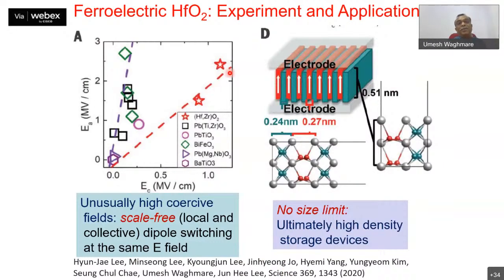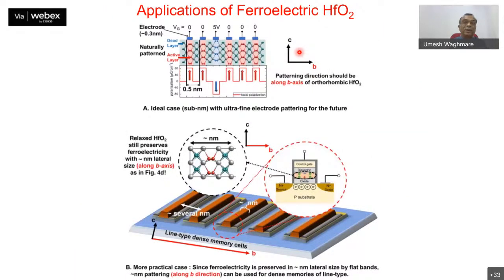The second thing where hafnium oxide stands out in terms of its ferroelectricity is that all conventional ferroelectrics have very low coercive electric field, the switching field, in comparison with the activation field, whereas in hafnium oxide, the two fields are equal. And the reason for it is that ferroelectricity in hafnium oxide is basically scale-free, and it means you can have ferroelectric dipole sheets at any length scale that you like. And as a result, there is no size limit on ferroelectricity in hafnium oxide, neither lateral nor transverse. Okay, and as a result, ultimately high density storage devices can be developed using hafnium oxide ferroelectricity.